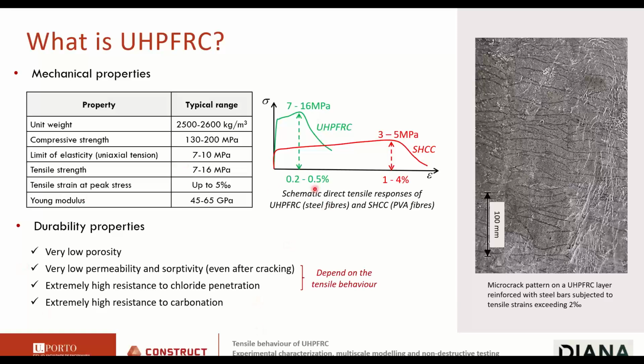Another important property of UHPFRC is the durability. Due to the very low porosity, low permeability and sorptivity of the very compact matrix, it's extremely resistant to chloride penetration, extremely resistant to carbonation. So it's a good material to apply in very demanding environmental exposure conditions. But some of these durability properties depend on the tensile behavior. If you have a UHPFRC that is capable of forming this tight array of cracks, then it means that it can maintain its durability properties even under large tensile strains.